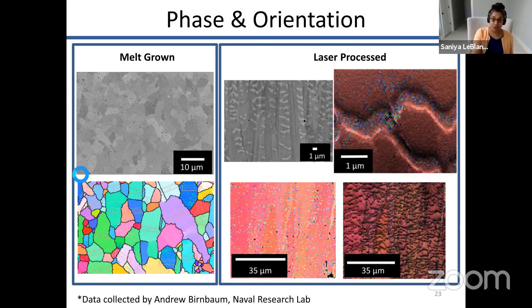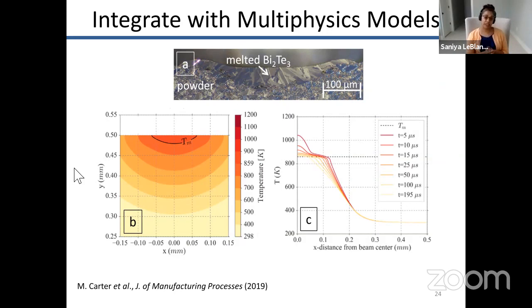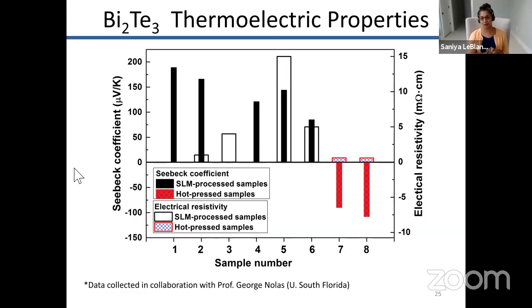And so we develop that understanding by building multiphysics models that allow us to understand what the temperature gradient is in the material while it's being processed. And we connect that understanding with the structure that develops in the material. So we understand the temperature gradients, how those gradients change over time, and we can look at the structuring that develops in the material. And then finally, we look at the transport property. We look at how it affects the Seebeck coefficient, which is this critical material property for the material. And what we found in our early studies is that it actually really changes. It can really change the Seebeck coefficient.